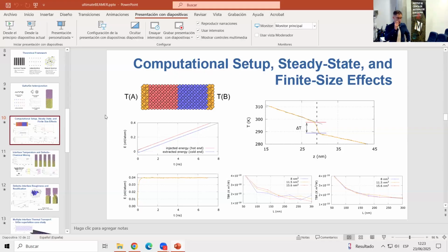So every phonon which hits on the interface has a lesser chance to actually find an available phonon state on the other side, so it cannot go there. This is why you observe a higher thermal boundary resistance. More phonons get scattered back.